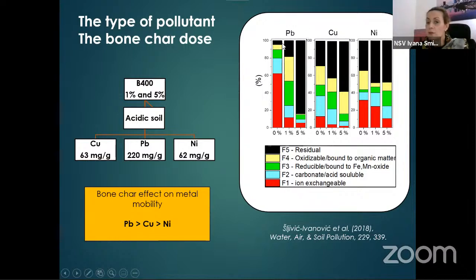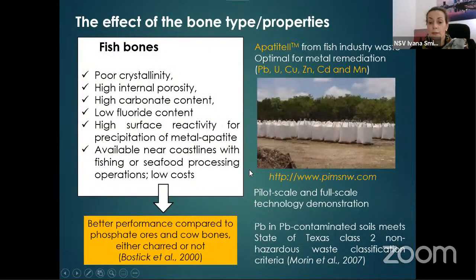The lead was most efficiently immobilized, and it was practically transferred from the ion exchangeable to the residual fraction, and then the effect was pronounced for copper and then for nickel. So the type of pollutants must also be taken into account when the remediation technique is developed.